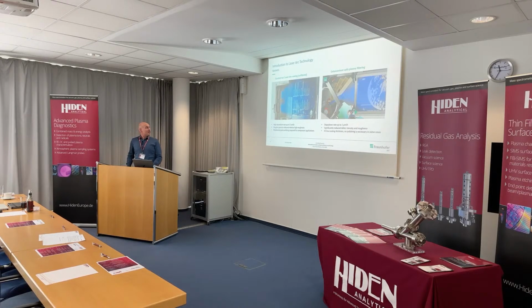This is how the two types of our coating machines and plasma modules look. On the left side, you have a high deposition rate variant, up to 2 micrometers an hour. Mostly we are limited by the temperature we put in the chamber. If you want to grow carbon, you need to stay at lower temperatures, below 100 degrees C, and the higher you get in temperature, the softer your films get. That means at 180 degrees C, you don't get any sp3 coatings anymore. Then you have to cool your sample holder or reduce the deposition rate. So we could be limited also by this.